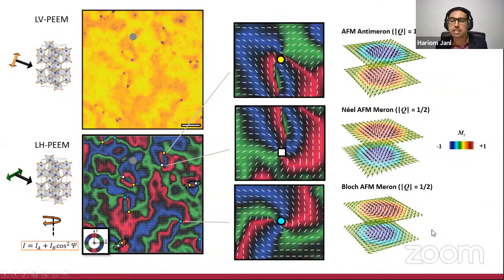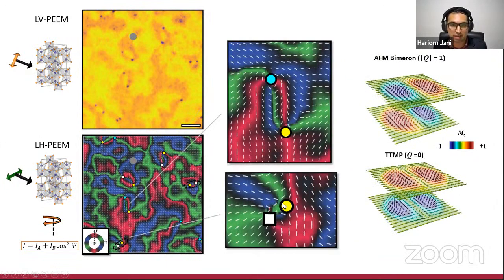Now, apart from these individual entities, we can also see various pairs which are present across the sample. I'm just zooming into two of them, which are at some little distance or at some extremely close proximity with respect to each other. In some sense, as you can see, this is almost resolution limited as far as this technique goes, which is almost down to 50 nanometers. So these are really tight objects.